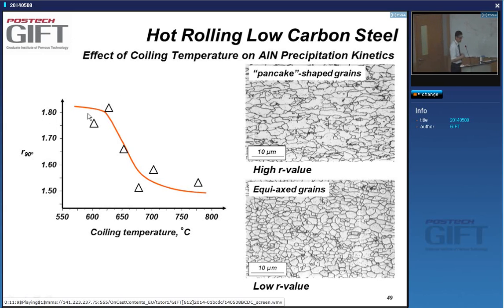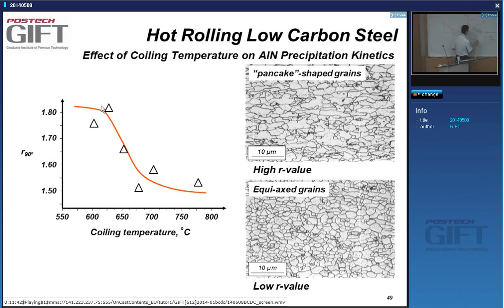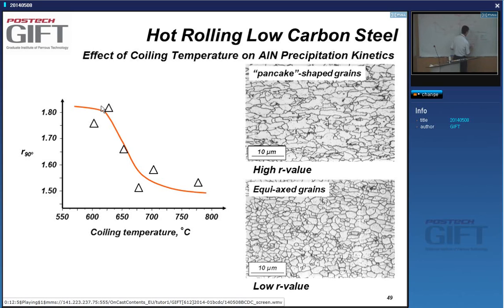In order to have aluminum nitride precipitating during batch annealing, you must have aluminum nitride in solution. This is achieved by controlling the coiling temperature in the hot strip mill. When the coiling temperature is low — 600°C and below — aluminum nitride stays in solution, giving a high R value. If you coil above 650°C, aluminum nitride precipitates in the coiled strip, resulting in a much lower R value.